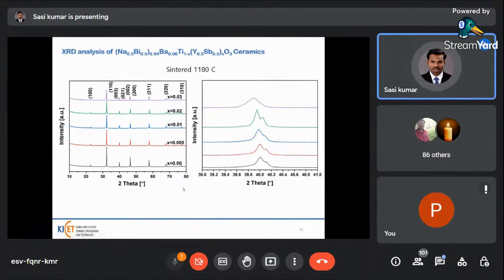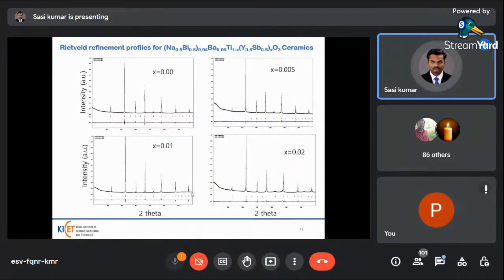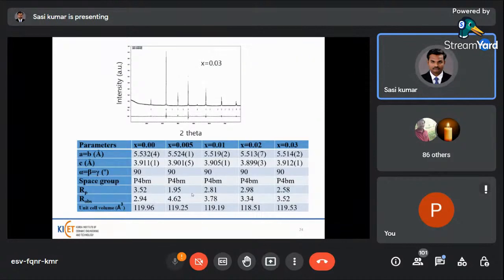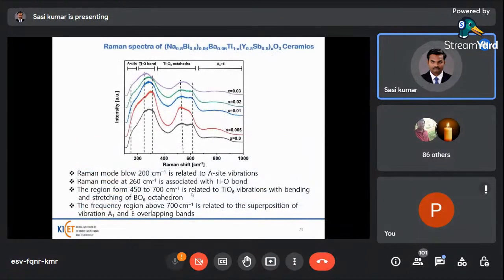This is the powder XRD patterns of the different compositions. When you add the higher composition, the peaks are shifted towards the lower angle side of 2 theta. And then Rietveld refinement profiles of NBBT and yttrium and Sb doped materials. Here, these are the structural parameters of NBBT, yttrium and Sb doped material. And then this is the Raman spectra of this.